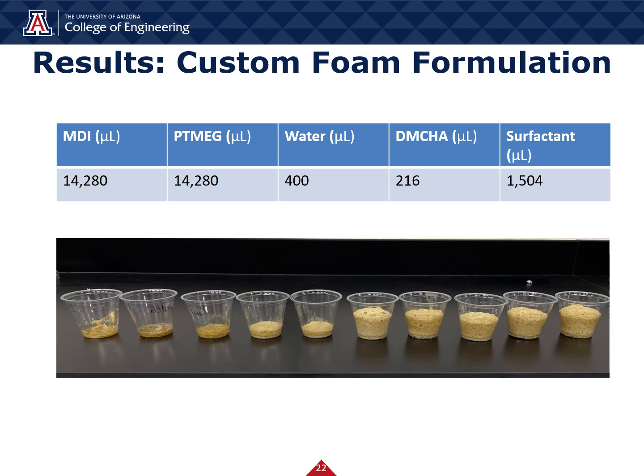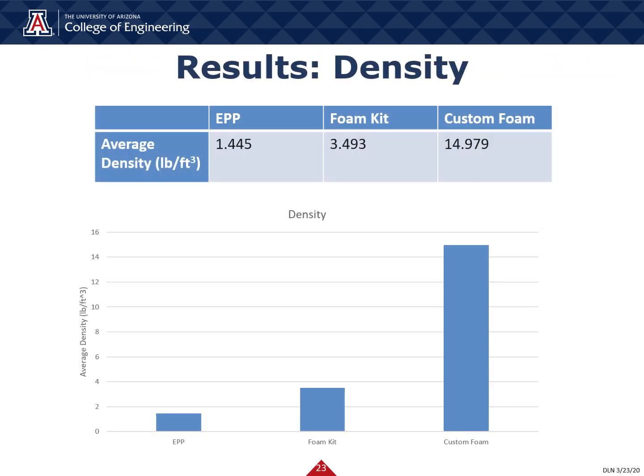Here you can see the results of our foam formulation iterations. The formulation for iteration number 9 is pictured. This formulation resulted in the foam with the most uniform cell size, so we used it for making our test samples. The density of each foam formulation was calculated by measuring the mass of a foam sample of known volume, and the averages are shown.